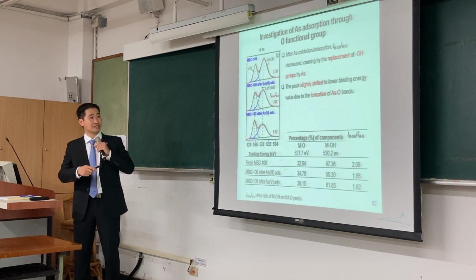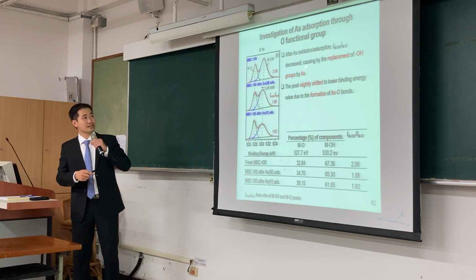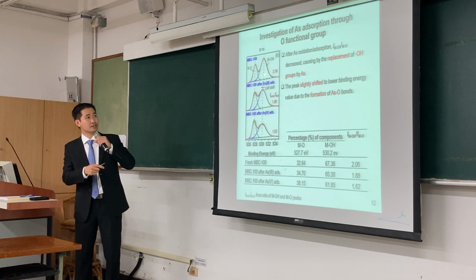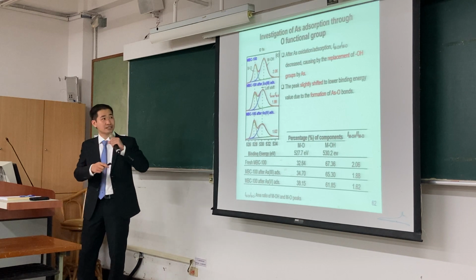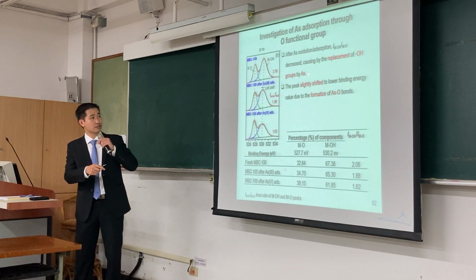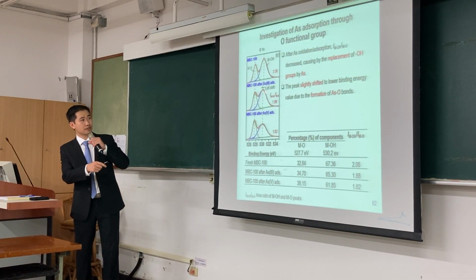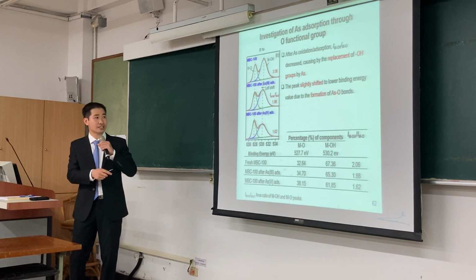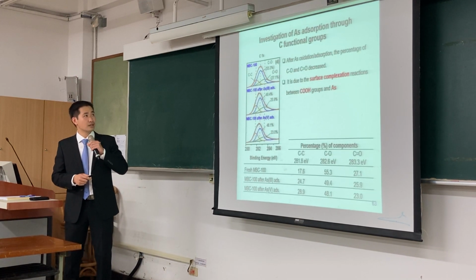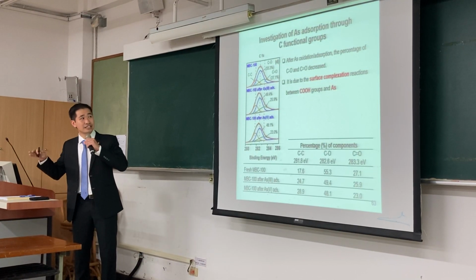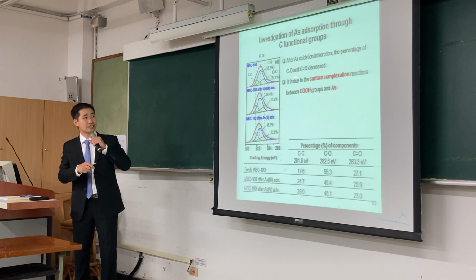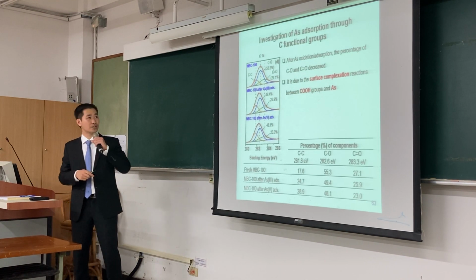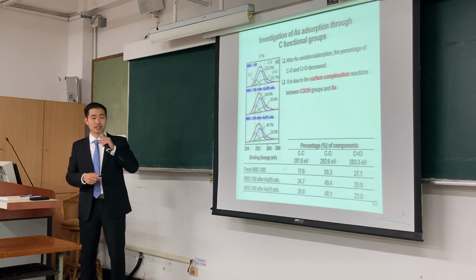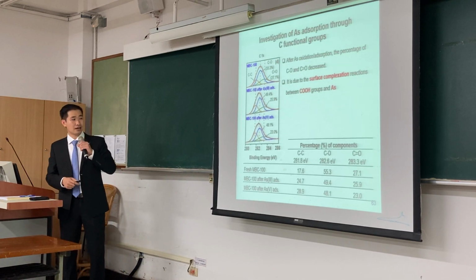The arsenic adsorption mechanism was investigated. We can see that after arsenic oxidation and adsorption, the ratio of the peak between OH and O is decreased, caused by the replacement of the oxygen of the OH group by arsenic. Also, a slight shift to lower energy is present for the arsenic adsorption. After arsenic oxidation and adsorption, the percentage of this group decreased. It may be due to a complexation reaction between carboxyls and arsenic.